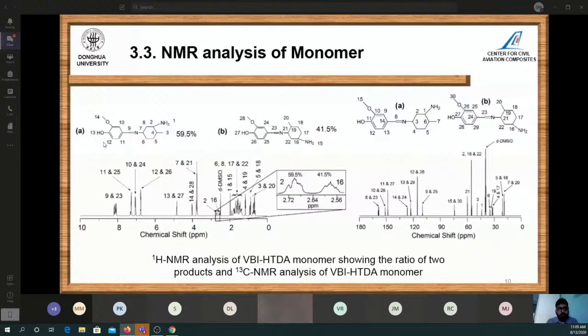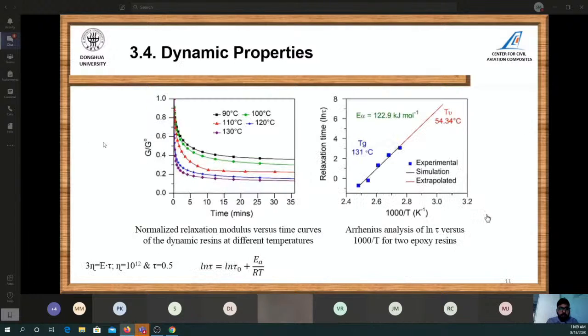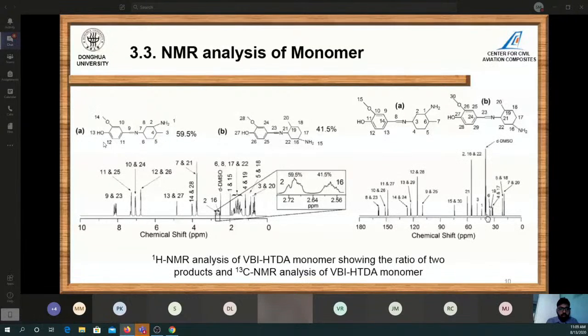We analyzed this structure because it's shown in the scheme that there were the two types, A and B. They were the structural monomers of this VBI-HTDA during the synthesis. So we also determined what was the ratio of A versus B, like it was 59.5 and 41.5, that we calculated using HNMR. That there are the two main compounds. And then we also did the dynamic properties analysis. Also we did the CNMR analysis that is shown here.